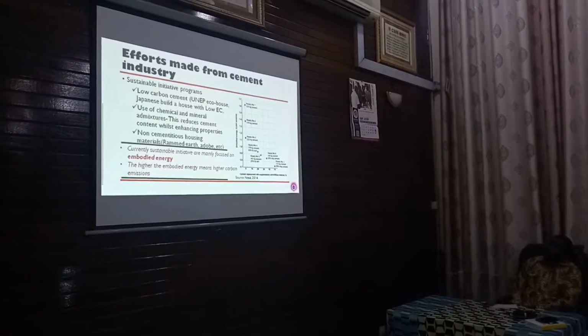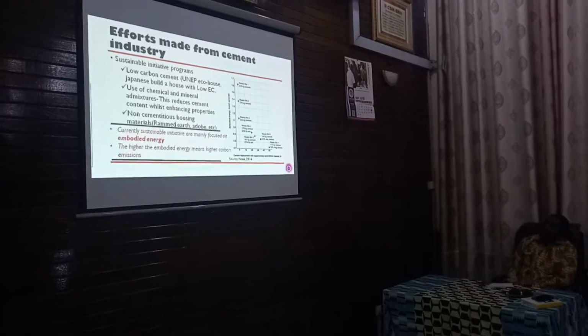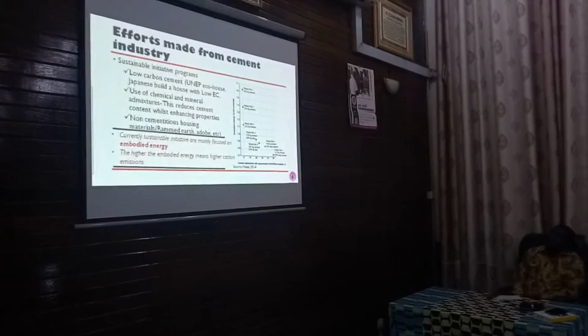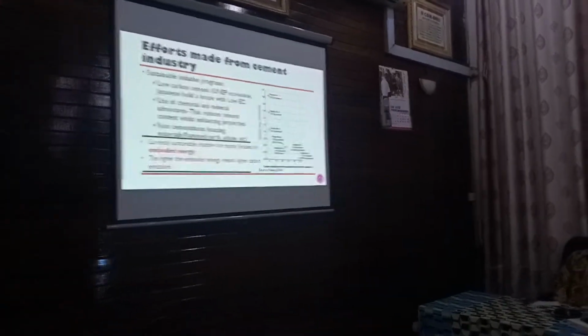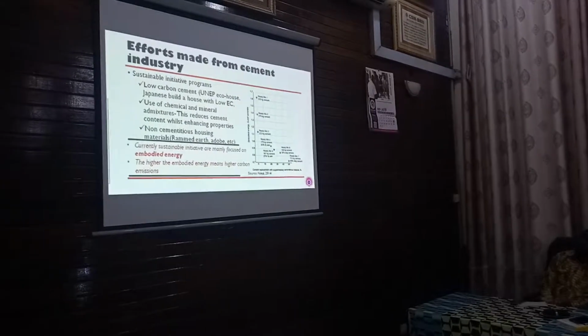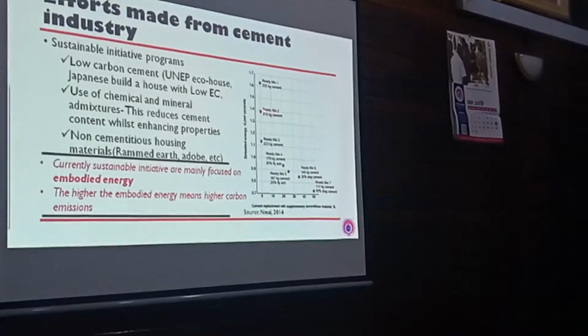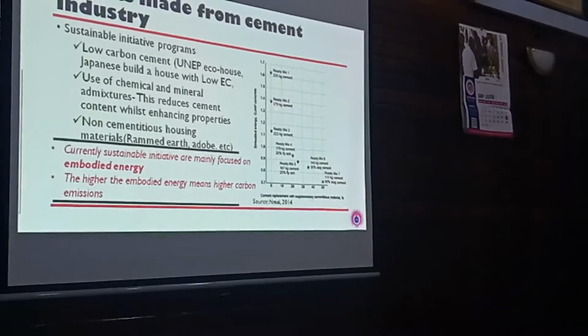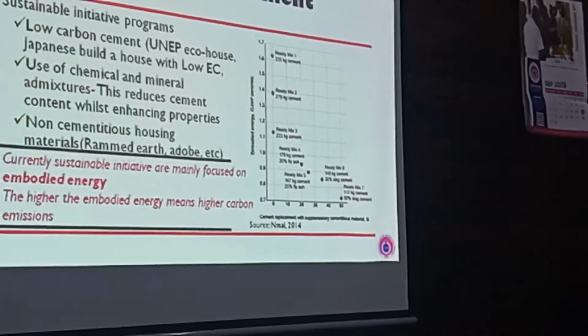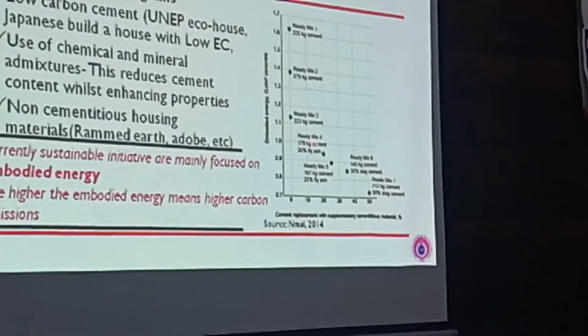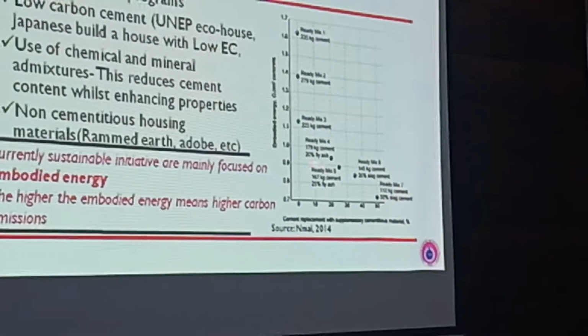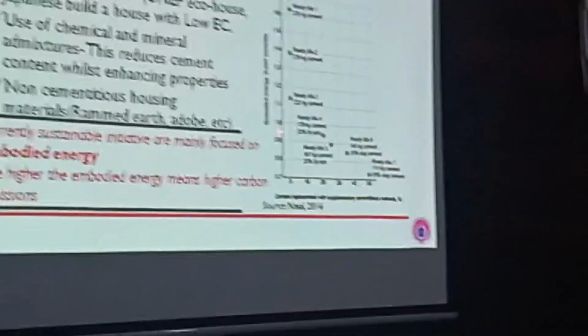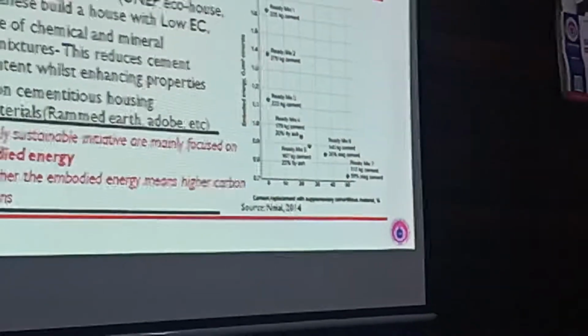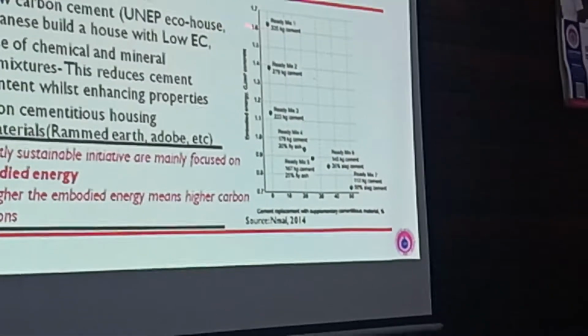Now the Portland Cement Association did a research where they compared concrete without admixtures with concrete with admixtures. So if you go to the top here, you see that we have a ready mixed concrete containing about 335 kilograms of cement. Now this one too is a ready mixed concrete containing about 279 kilograms of cement. But then if you come here, they replaced the content of cement with about 20% fly ash, and look, the embodied energy was less than 1.0, as compared to this one without anything.